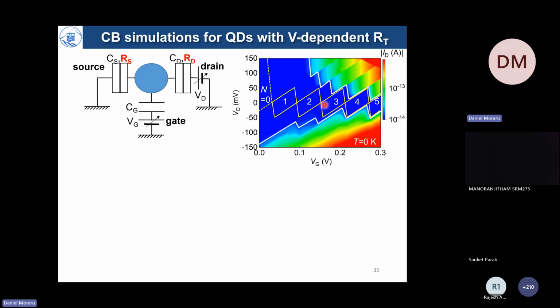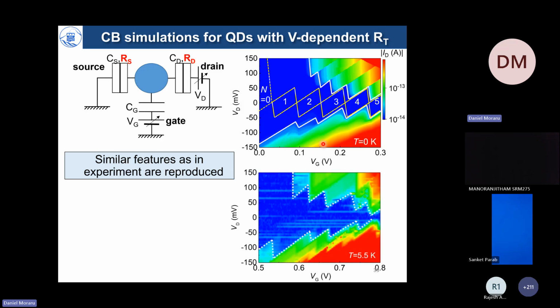With this, we could simulate the stability diagrams again, and the yellow lines here illustrate what would happen in an ideal case when we could measure the current very precisely. We should observe closed Coulomb diamonds, equally spaced and of equal height, from the consecutive addition of electrons from 0 to 5 electrons, let's say, in this range of VG. However, what we really observed was a shape like an open mouth for this device. The reason for that is indeed the sensitivity of the resistances to this operation. So now we can understand why this structure is observed. It is because the resistance increases as we make the gate voltage more and more negative.